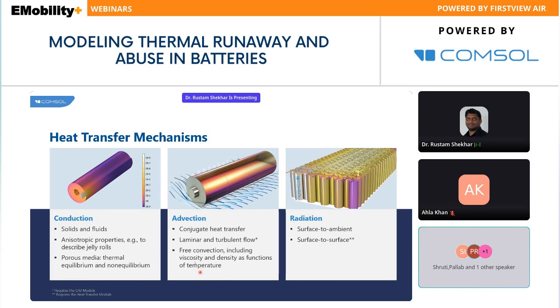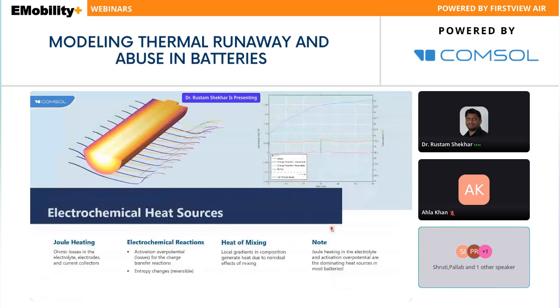But when you want to design the cooling mechanisms, then advection, which will be the conjugate heat transfer, can show up. So then you can do the advection part as well. And in some cases, if you are interested, which is very rare in battery modeling, the radiation part, then you can add that as well, which will be surface to surface and surface to ambient. In some cases, radiation also helps you cool down hot environments or hot surfaces. So then you can design the surface to ambient conditions as well.